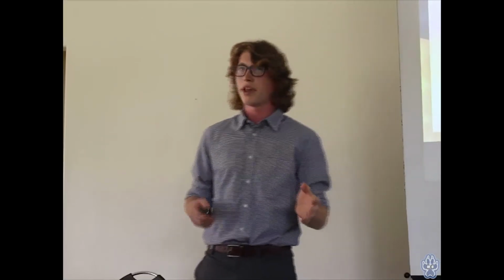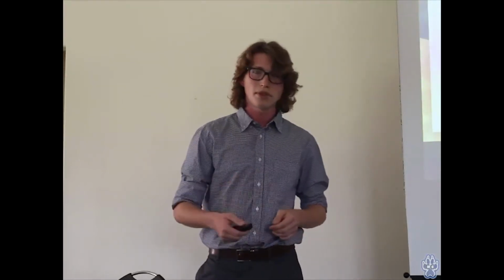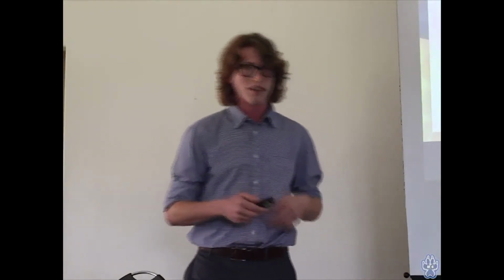So we decided, okay, we want this layer to stick, so let's do an extended second anodization overnight for about 15 hours. Maybe that'll make something thick enough to really stick to the surface. So we ran this, got the sample, and I rinsed it off, blew it with air, and the entire thing blew off. Okay, well, still close.